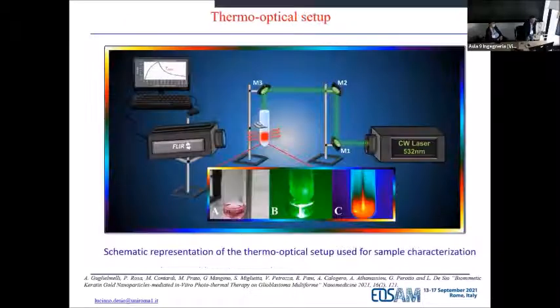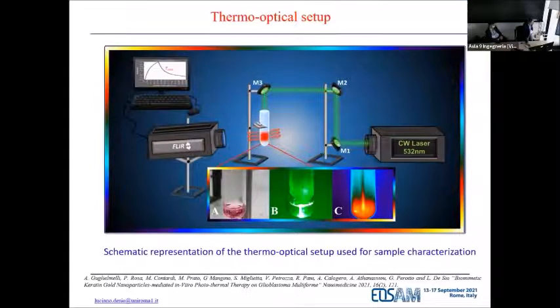So something else we did, once we were sure about the beauty of our particles, was to test in operational mode. So what we do, we have cells here in the solution with, of course, gold nanoparticles. We shine on a suitable light source, which is a green laser. Green laser because for spherical particles, as you saw in the very beginning, the absorption is in the green part of the spectral range. We shine this green laser and we acquire with a thermal camera the side view to detect the temperature change due to the ability of gold nanoparticles to convert this external light to heating.